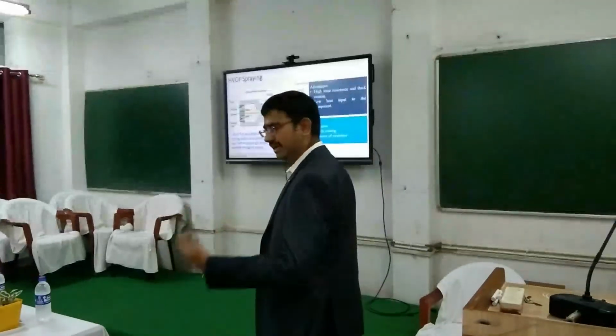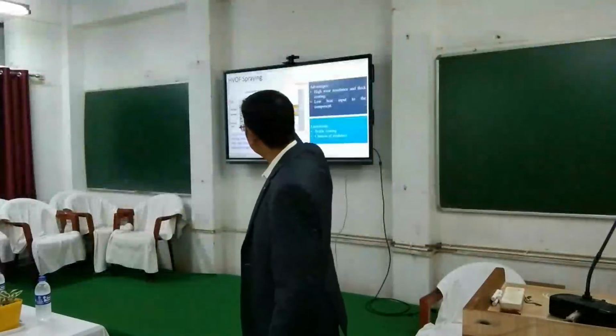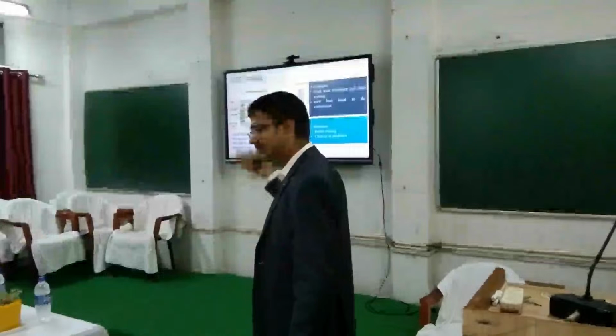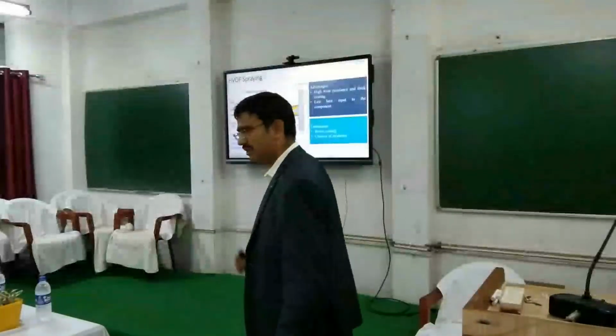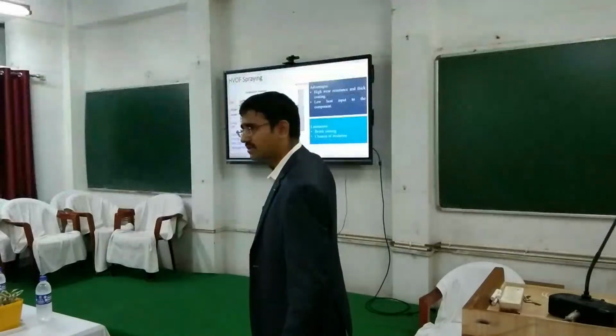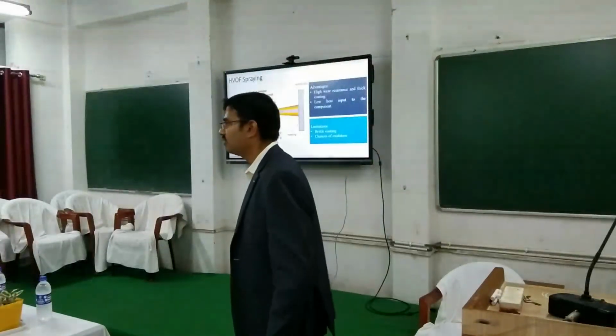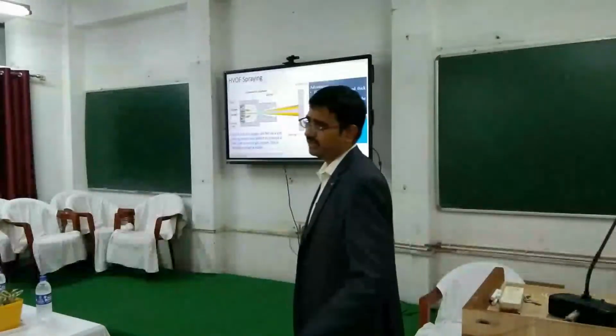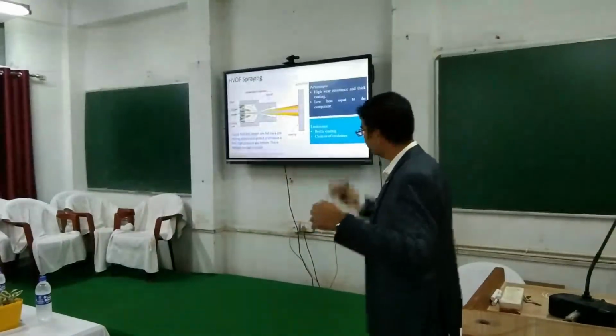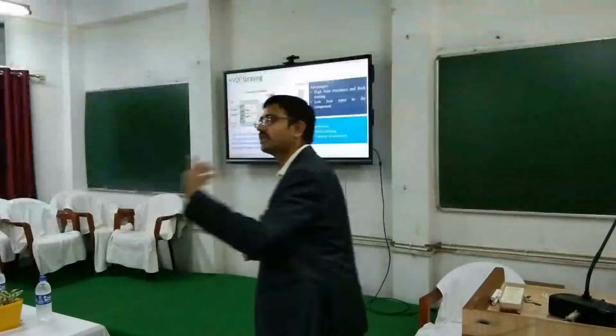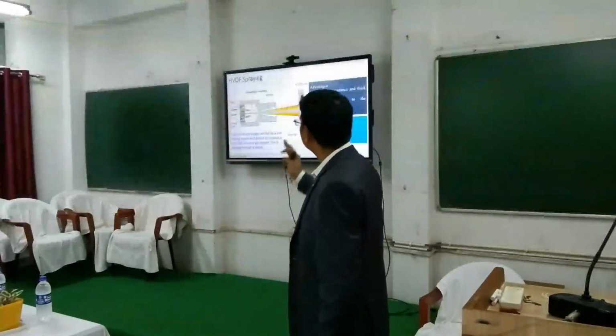Started to pick up. Oxyacetylene flames, welding also picked up. So that's why they started using oxygen and fuel typically. Here also sometimes they use kerosene or acetylene. So the oxy-fuel mixture is basically fed in. The powder is fed, it is combusted, and after combustion the gases are released and expanded through a convergent divergent nozzle. Earlier it was mostly a convergent nozzle, but here it is mostly a convergent divergent nozzle, so you get much more acceleration and velocities. So impact is at a higher rate.